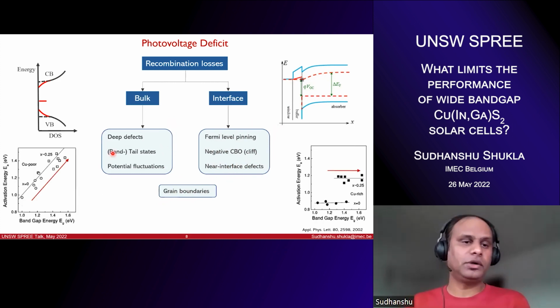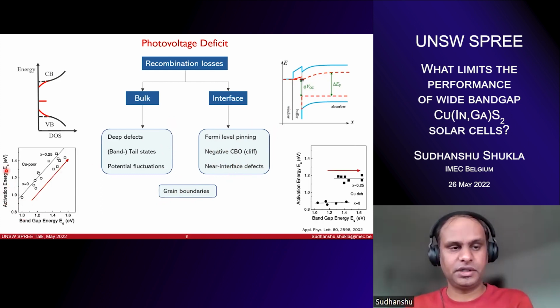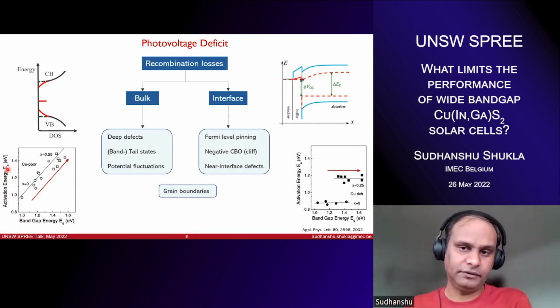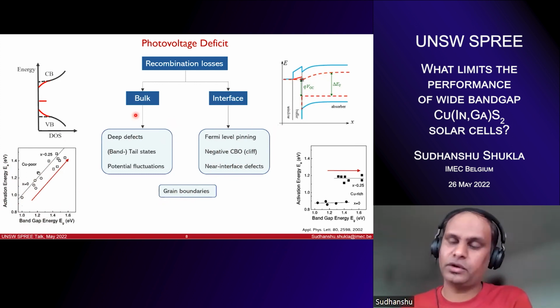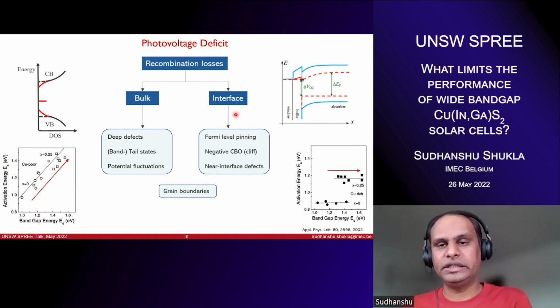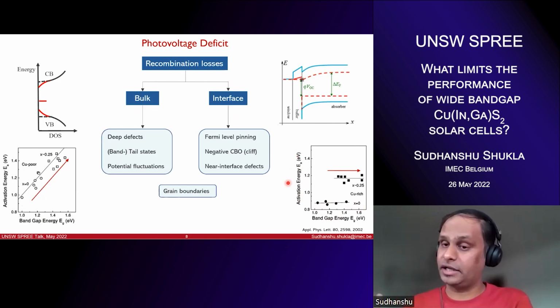If you have a bulk recombination, then what you see is the activation energy of recombination, if you derive it from your JV measurements, for example, scales with the band gap if you have a bulk recombination that is dominating. But if you have an interface recombination which is limiting your VOC, then your activation energies do not change if you increase the band gap, because the defect energy is actually fixed. No matter if you increase the band gap, the recombination is actually occurring at your interface. So this is a curve that you get when you are dealing with bulk recombination dominant, and when you have interface recombination.